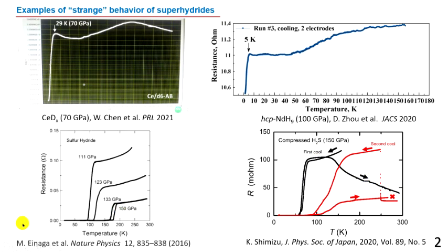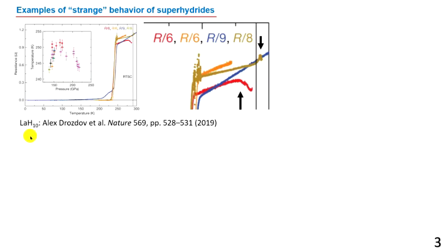And the last example I would like to show is a publication by M. Einaga in Nature Physics in 2016, one of the first publications about the sulfur hydride. We can see that during decomposition, the behavior of this hydride in the normal state changes, and at 111 GPa we see some upturn feature close to 250 kelvins, and this upturn feature should not exist in normal metals. We can see that it's non-Fermi-liquid behavior. Okay, let me give you several additional examples.